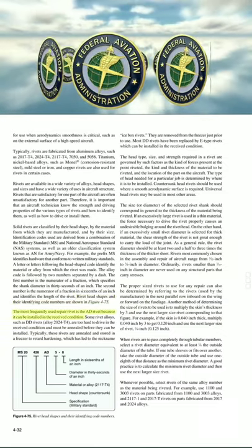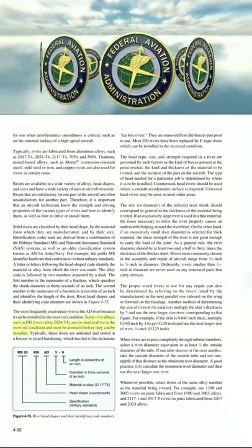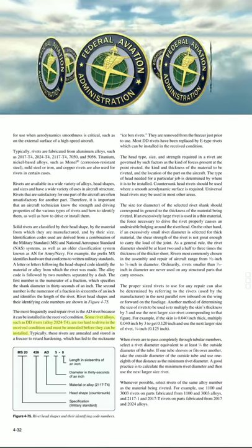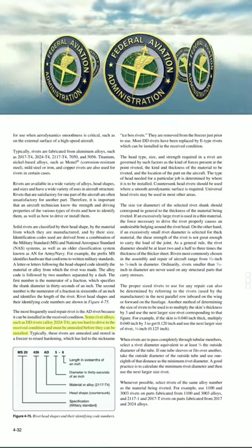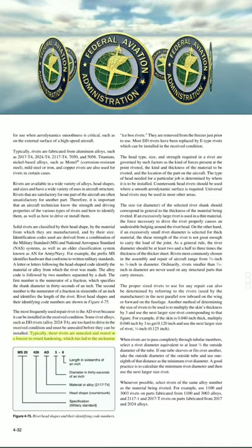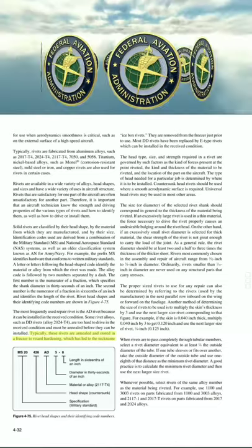The most frequently used repair rivet is the AD rivet, because it can be installed in the received condition. Some rivet alloys, such as DD rivets, alloy 2024T4, are too hard to drive in the received condition and must be annealed before they can be installed. Typically, these rivets are annealed and stored in a freezer to retard hardening, which has led to the nickname